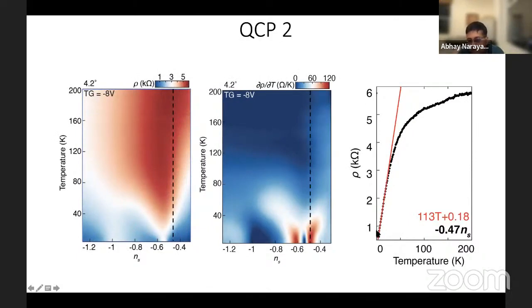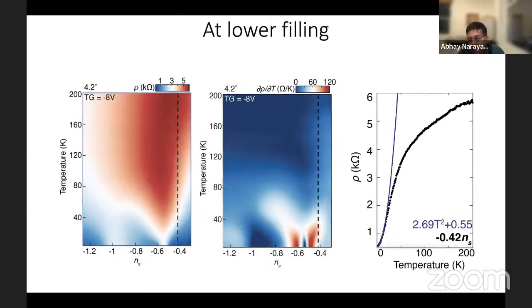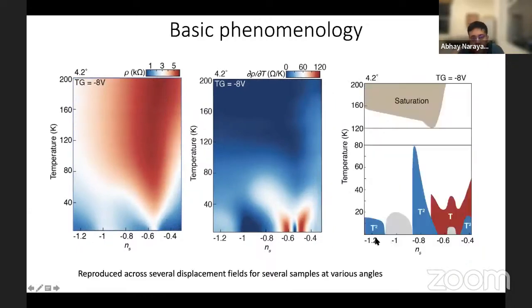once again, I see T-linear behavior down to low temperature. And if I go even further, then once again, it starts to curve and I start to see T-squared behavior reappear in the system. So I can summarize all of this data in this color-coded plot, which tells you in which range of temperature what power law fits the resistance well.